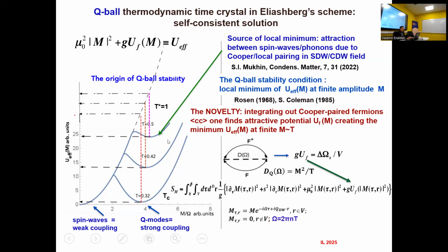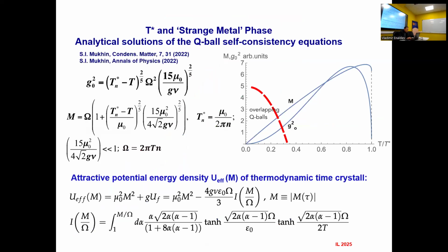So this is precisely the picture from Sidney Coleman's article for Q-ball formation. The only difference is that he considered real time in Minkowski space, and here it is finite temperature. And of course, he did not consider the origin of this minimum, while here the origin is strictly the Cooper pairing. Now we go further on, and we can solve the self-consistency equation close to this T star temperature. Here, if you take n equals 1, this is the highest T star temperature, and then you see that the superconducting gap squared behaves like this. At T star, the superconducting gap becomes 0.